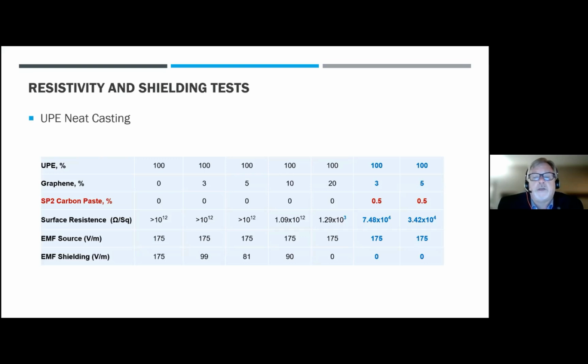and you're seeing good conductivity. So you finally get that graphene component into that composite material, the thermoset material, and you're starting to see the properties that we're looking for here. Now, if we step back a little bit and we go to where we're adding 3% graphene, we just add 0.5% of our SP2 carbon paste, which is our additive that's been specially formulated to be compatible with unsaturated polyester. So that's where our technology comes in.